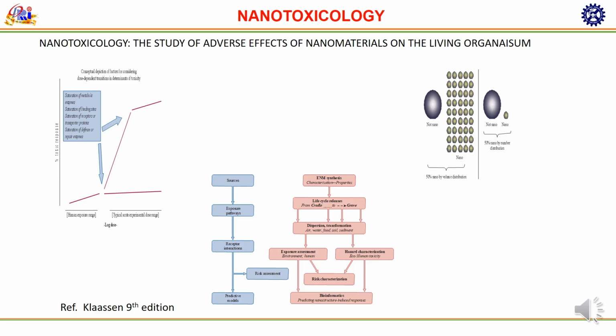Also, consider nanoparticle size and distribution. The same material can behave very differently at nanoscale. Compare 50% of volume versus 50% of number distribution. By volume, larger particles dominate the measurement, masking the nanosize fraction. By number, nanoparticles appear more dominant due to their high count, even if they contribute less to overall mass. This highlights why nanoparticles cannot be assessed as bulk material, and their size and surface area control their behavior.